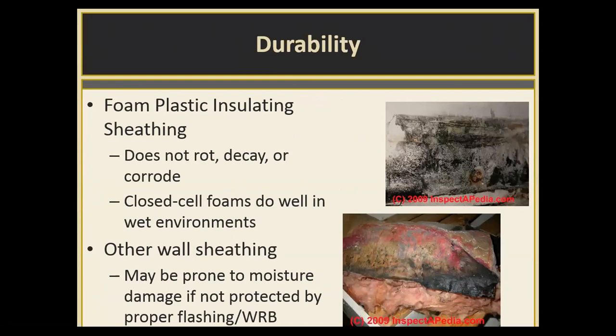When you talk about durability of continuous insulation products, rigid foam boards don't rot, decay, or corrode. Closed cell foams are just that. They're closed cells, so they don't absorb water, and they do very well in wet environments. Fibrous products, if they're not properly protected, can be prone to moisture damage because they will suck up water or trap it, which is not good for the wall assembly.